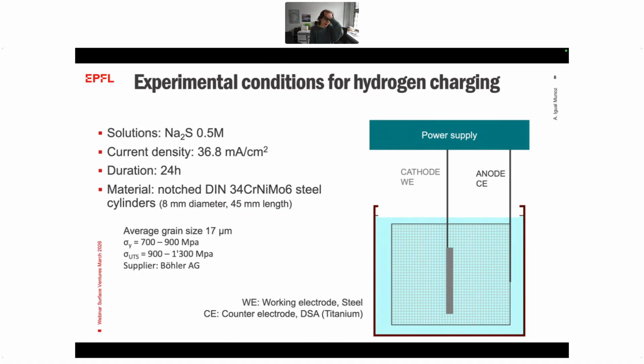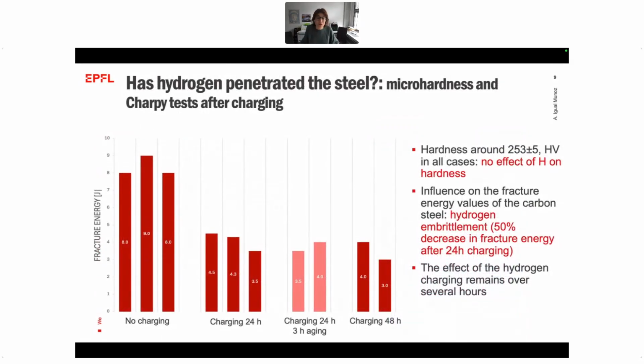Then we apply a certain current for 24 hours. In the first case, what we charged was a Charpy sample to try to identify the consequences of the charging on the properties of the material. So the first question, as I was saying before, is: has hydrogen penetrated the steel? The hardness didn't change at all before and after charging. However, the amount of energy absorbed by this steel during fracture decreased around 50% after charging for 24 hours.